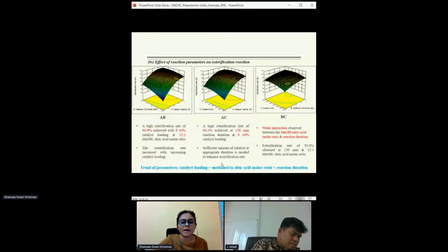Here is the optimization 3D surface, where the interaction between catalyst loading and methanol to oleic acid molar ratio contributed to a high esterification rate of 94.9% with 9 weight% catalyst loading and 12 to 1 methanol to oleic acid molar ratio. While the interaction between the catalyst loading and the reaction duration also achieved a high esterification rate of 94.1% at 150 minutes and 9 weight% of catalyst loading.